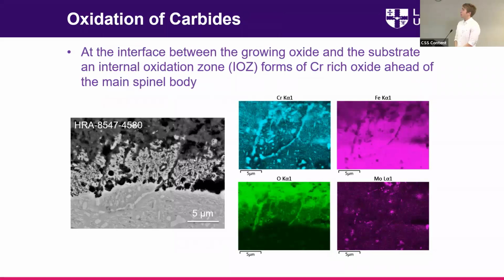At the interface between the spinel and the substrate, there's an internal oxidation zone that's penetrating into the substrate, and you can see that it's following the chromium-rich oxide within the internal oxidation zone, and it's following along the grain boundaries where you can see the carbides which are present. So it's showing that the oxidation of the steel is taking place through the preferential oxidation of the chromium, which is effectively almost dictated by where the previous carbides are formed, because the majority of them are chromium containing.